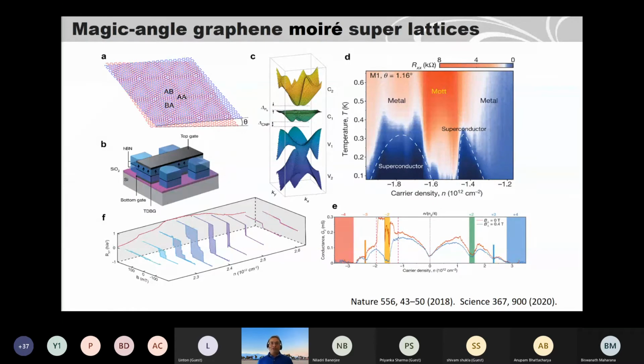Okay, what can be other interesting things one can study with spin transport in graphene, but with high quality graphene? As you know, in the last two to three years, lots of development happened with magic angle graphene. If you twist two graphene layers at a small angle, like 1.1 degree, between the top and bottom layer of graphene, and this is then encapsulated with high quality boron nitride, then what you see is that the band structure completely changes.